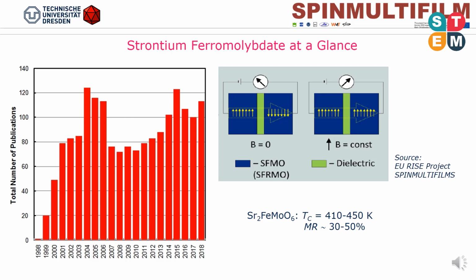Oxide perovskites with ferromagnetic behavior around room temperature were first reported in the 1950s in the pioneering studies on manganites. The discovery of the low-field magnetoresistance and half-metallicity of strontium ferromolybdate by Kobayashi in 1998 renewed the interest in these materials in the context of their potential application in the field of spin electronics. In the following years, the number of publications replicates the Gartner hype cycle for emerging technologies: an innovation trigger, a peak of inflated expectations, a trough of disillusionment, and a slope of enlightenment. What is still absent is a plateau of productivity.